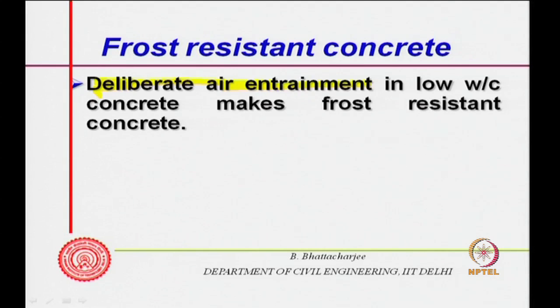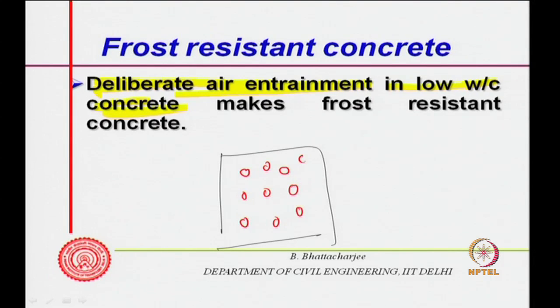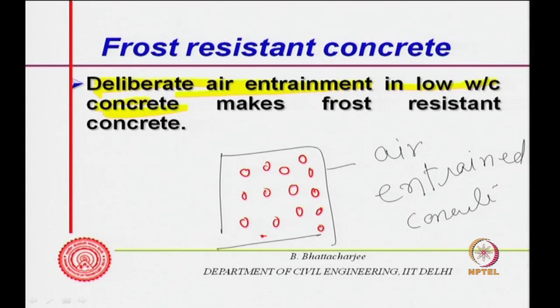So, deliberate air entrainment in low water cement ratio concrete. Now, low water cement ratio concrete will allow less water ingress. And if I have air entrainment, what will air entrainment do? If this is your concrete, it will create a sort of isolated small pore system, spherical, well distributed. So, they are well distributed fine pores, but closed pores.